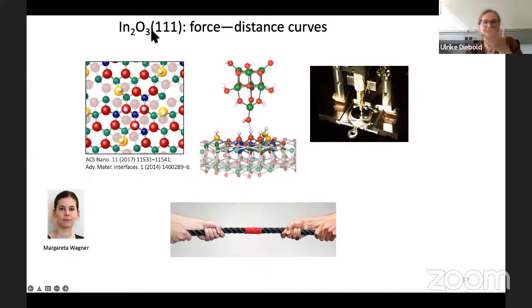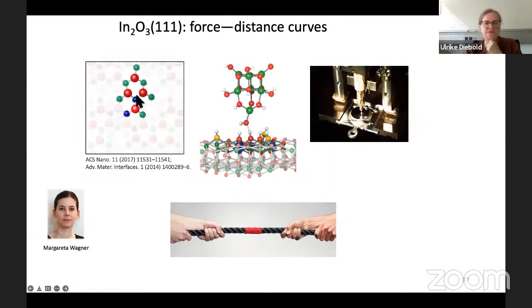She did this on this particular oxide surface. There's lots of interest in why, but I will not go into any of the details. This is just the atomic model of the surface. Maybe the only thing that's interesting in this context is that this is a very perfect single crystalline surface, and we have four types of oxygen atoms. The red are the oxygen atoms and green and blue are the indium atoms. Each of these oxygen atoms is bound to 3 indiums in a slightly different way. So the bond angle and the bond distance of these oxygen atoms with the cations is a little bit different.